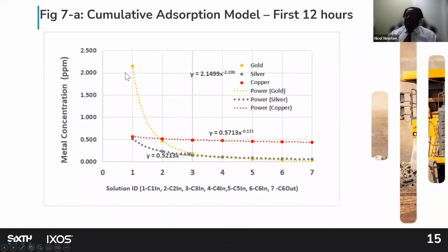Now, with that information, we did try to see what was actually happening at each point across the adsorption circuit, in particular with reference to column 1 through to column 6. And using a statistical method, we derived a curve to see the recovery of the different metals for each hour that we had the plant running. In this particular case, we looked at the first 12 hours to see how the adsorption kinetics was behaving.